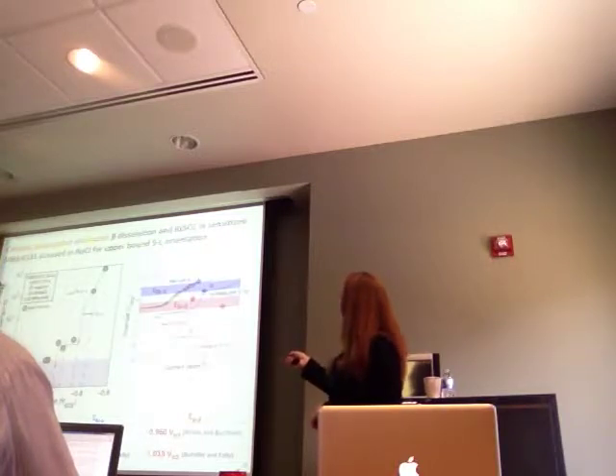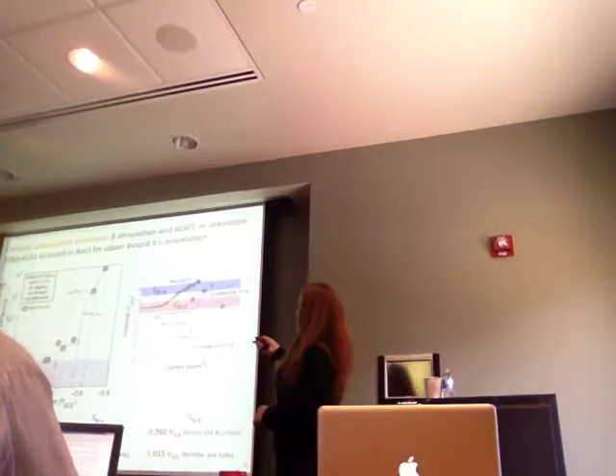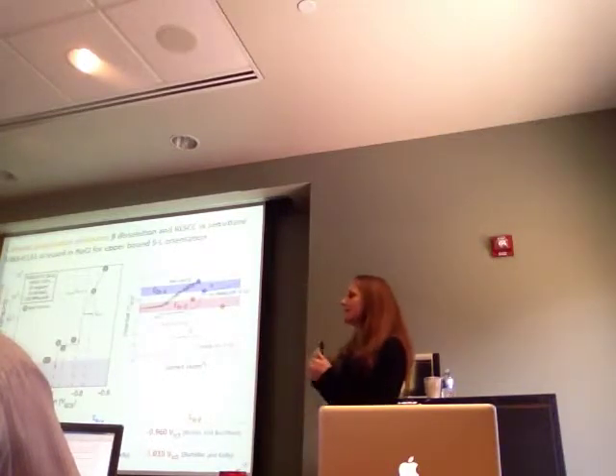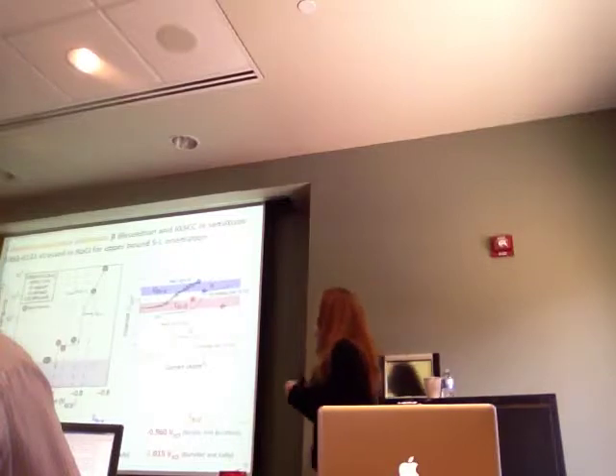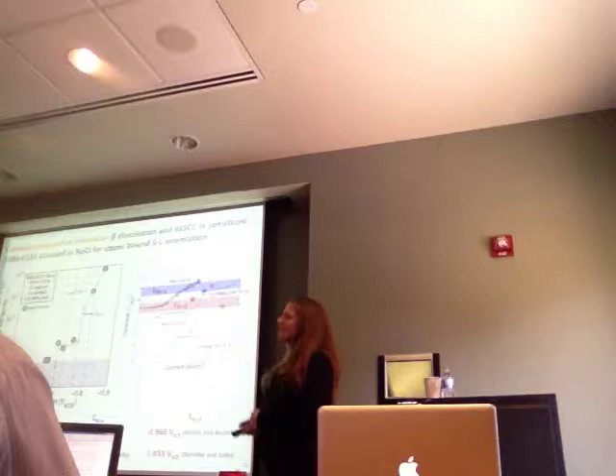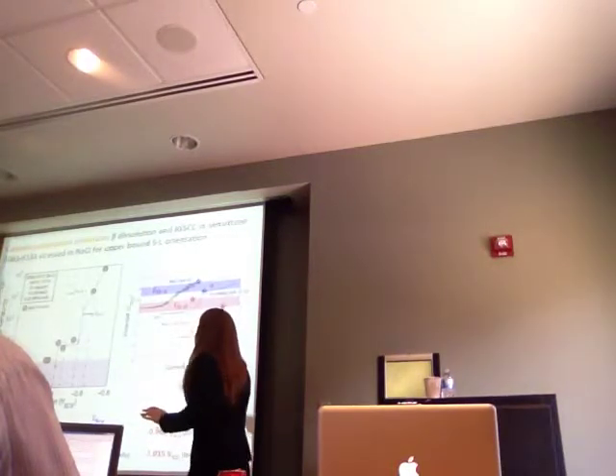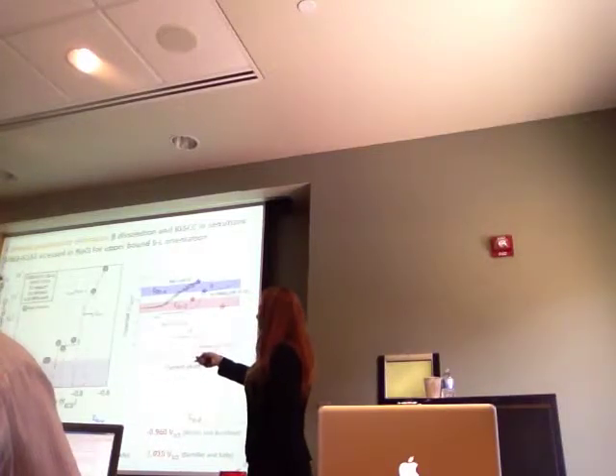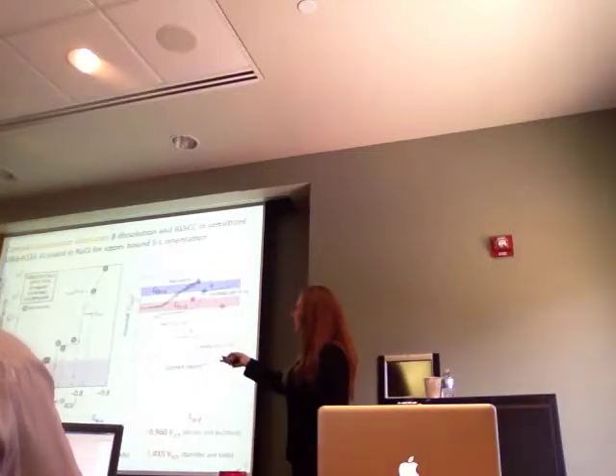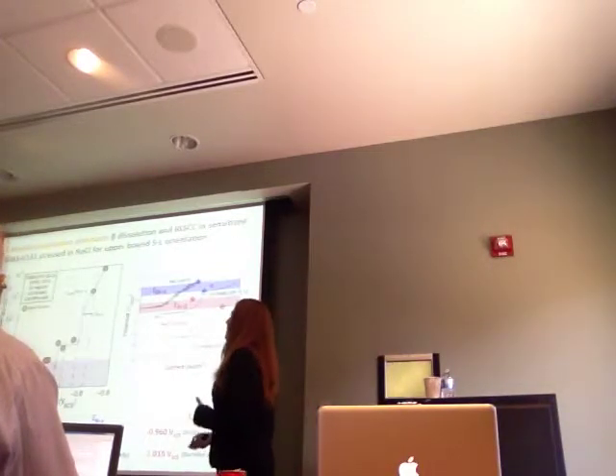I've also put this in an acidic crack-tip solution that's here. So this other blue star shows you that the breakdown potential actually drops. And you have this nice range between a very highly acidic crack-tip solution and a neutral solution. Your breakdown potential is dependent on your pH. And I plotted that range here. And you can see that once you get below that breakdown potential of alpha, your crack growth rate drops significantly. So it's basically because we're turning off the dissolution of the alpha phase, or we're making it passive.